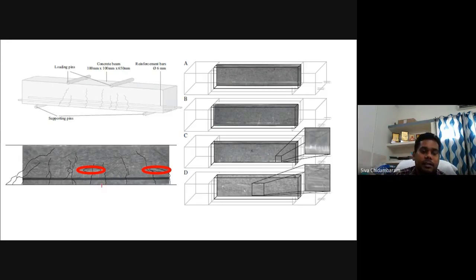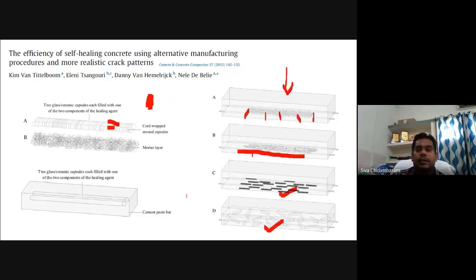For example, they have applied it like this, and then they have a number of cracks. Wherever I have made the red color mark, the capsules are present. The capsules are getting cracked, and you can see the epoxy infiltration through the cracks. Once ultraviolet light is passed over these, or otherwise when the adhesive is exposed to sunlight, generally it matures and becomes hardened and connects the cracked surface. This is a small introduction about self-healing concrete. So this is how self-healing concrete works and helps you to arrest the formation of minor cracks in structures.